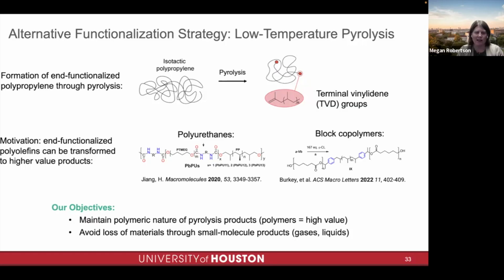And this is another way, which is very relevant to the advanced recycling work that's going on in the Houston area, which is through pyrolysis. Except in our case, we're very interested in retaining the polymeric nature of the material after pyrolysis. So instead of forming oils or waxes, or even ultimately smaller molecules, we want to use pyrolysis to functionalize the polymer without losing that solid polymer nature of the material.